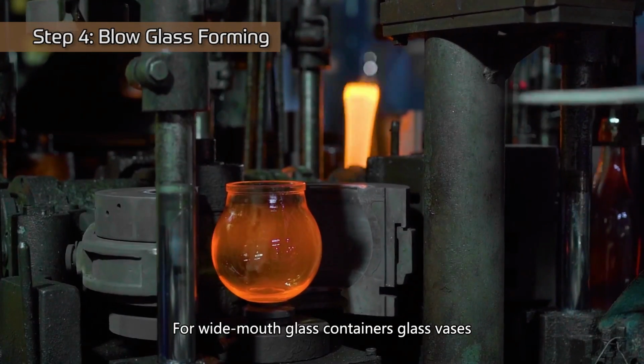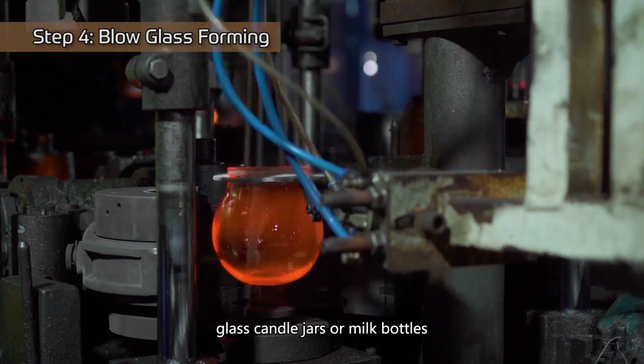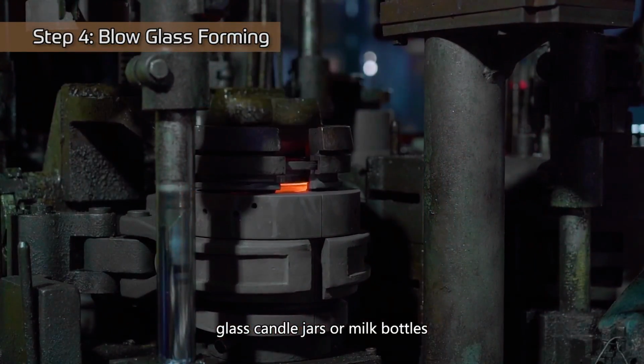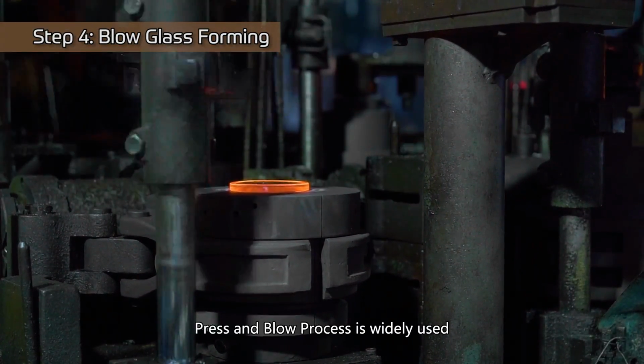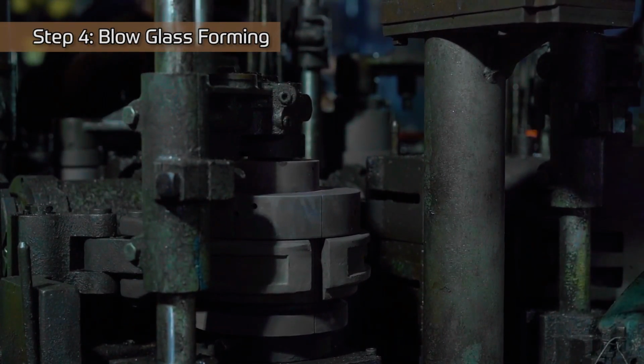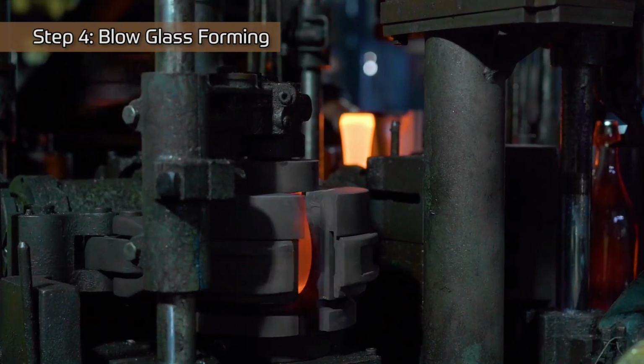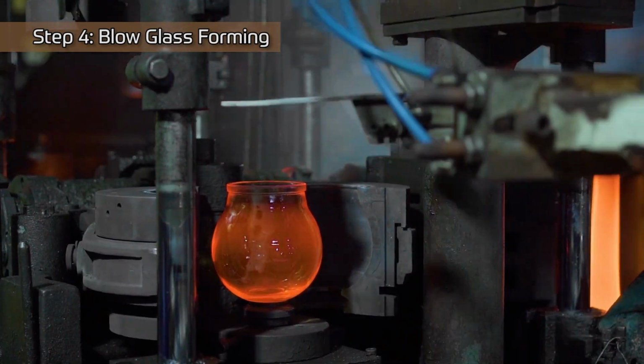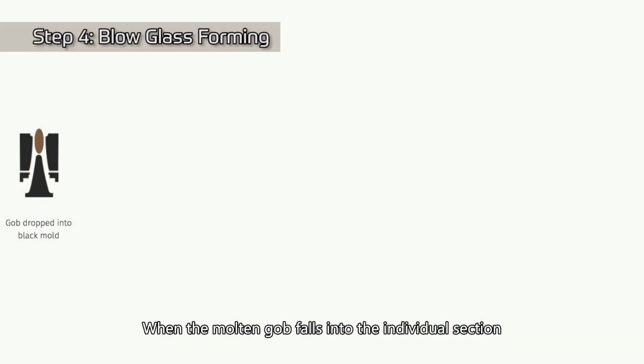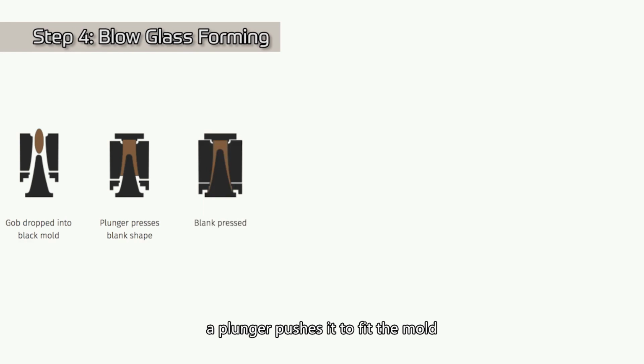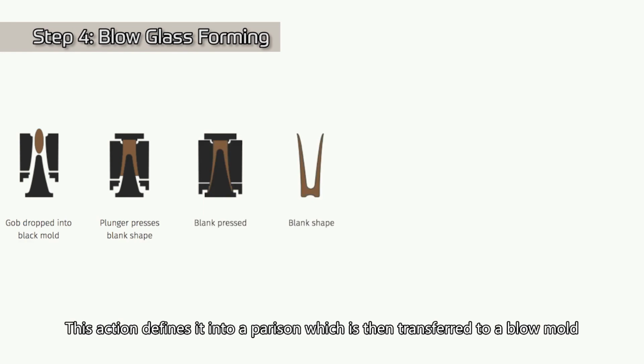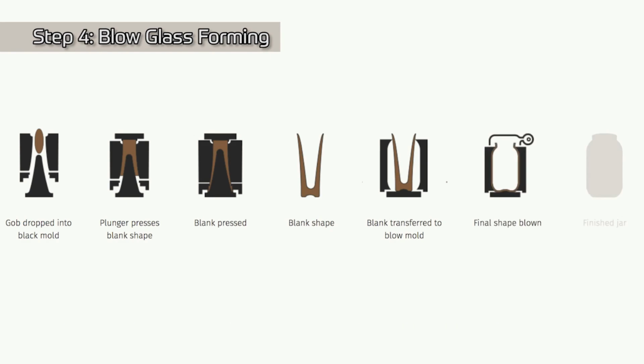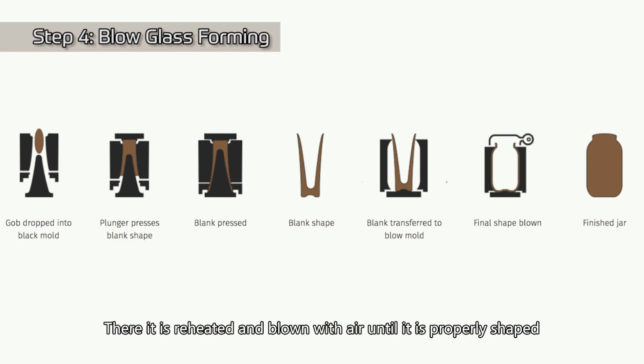For wide-mouth glass containers, glass vases, glass candle jars, or milk bottles, press and blow process is widely used. When the molten gob falls into the individual section, a plunger pushes it to fit the mold. This action defines it into a parison, which is then transferred to a blow mold. There, it is reheated and blown with air until it is properly shaped.